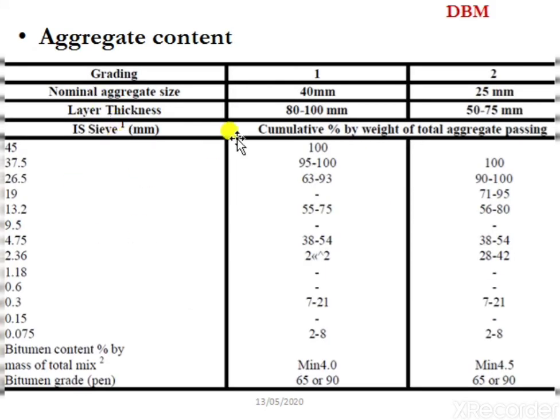These tests and values are almost similar to those of the previous pavement type. In this slide we can see a table showing the different gradings of aggregate, grade 1 and grade 2. In grade 1, the nominal aggregate size is 40 millimeter and the thickness of layer varies between 80 to 100 millimeter.